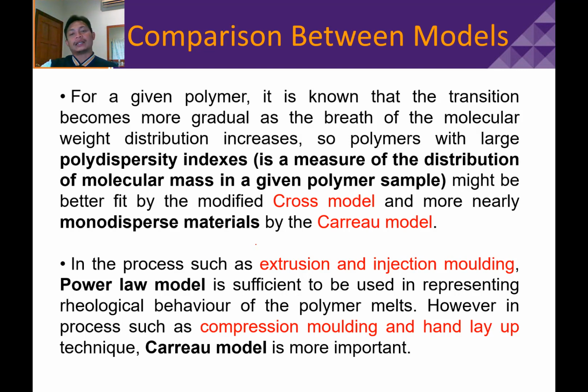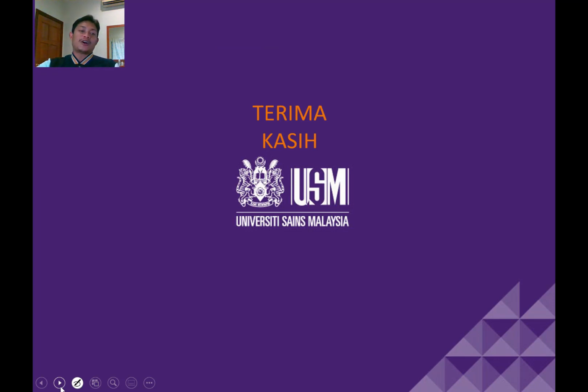Another consideration: if the process you use is extrusion or injection molding, you should use the power law model. However, for processes such as compression molding and hand lay-up, you can use the Carreau model to suit it well. I think that is all for our lecture.